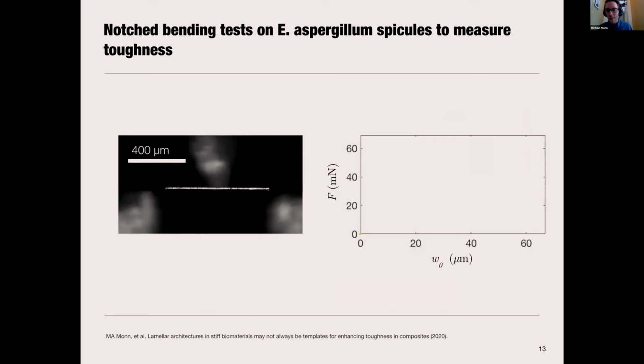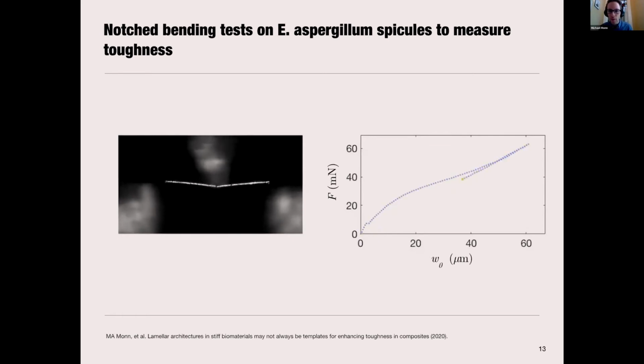So here's, again, to start getting really into the experiment, a video of the experiment on the left. You'll see this horizontal line, that's the spicule. It's illuminated collinearly on axis, so that's some reflected light that you see off of the curved surface. And then on the right-hand side, you'll see a force displacement curve following the video of the sample deflecting. This is sped up 48 times, and you can see this is the response that we get. So we performed a load and then an unload on the sample. I'll show you that one more time. A load, and then we unload the sample again in 1 micron increments.